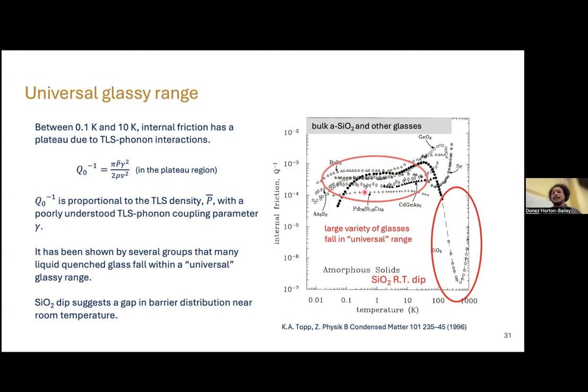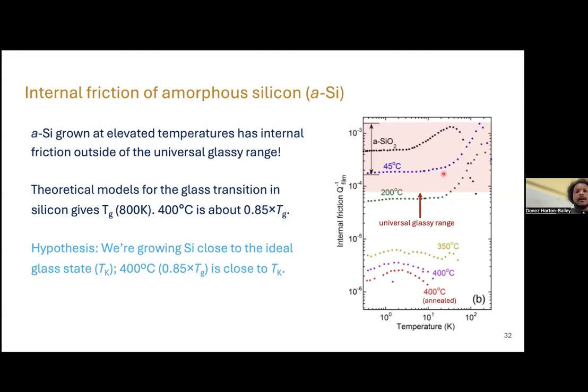And so ideally, we're trying to find some sort of glass whose plateau would fall below this region. And so it's believed that the height of this plateau is proportional to the number of TLS in your system. So the lower this plateau is, the fewer of these tunneling systems that we have. And so at lower temperatures, this is more relevant for stuff like quantum computing because those operate at cryogenic temperatures. At higher temperatures, this is more relevant for things like LIGO, where the mirrors are at room temperature. And so we see different behavior at different temperatures.